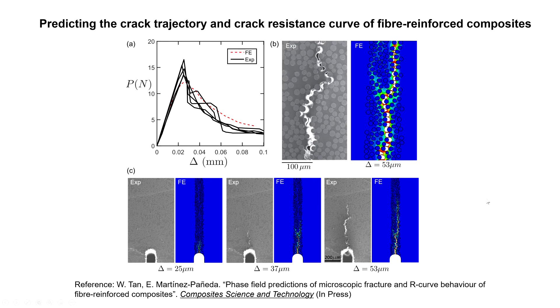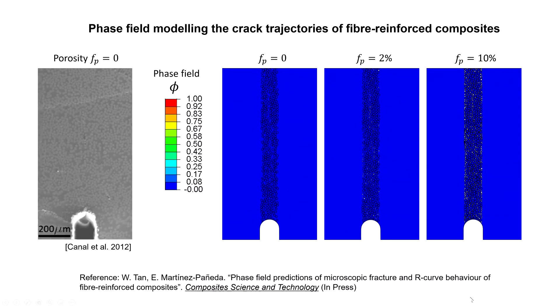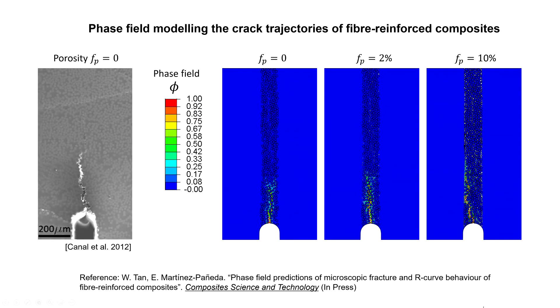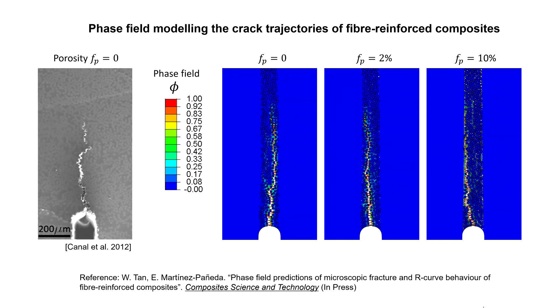The results show that we can capture the force-displacement curve quite accurately. We can also capture the crack trajectory, which represents fiber-matrix debonding and matrix bridging at the fracture process zone. We capture these complex fracture behaviors very accurately. Here is a video showing the crack propagation as the specimen is loaded.